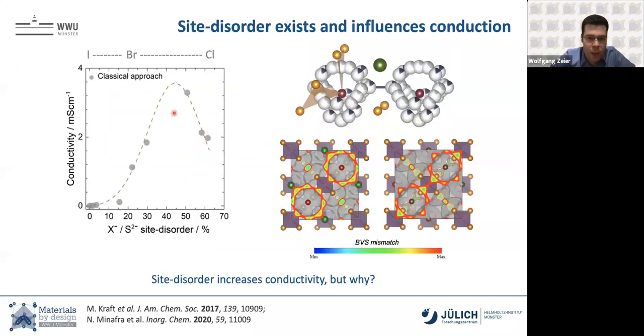Well, why certain compositions? There's something that we call site disorder in these materials. What is actually found is that depending on the halide that you use, some of the halide could be sitting on the sulfur site. This is very prominent in the chlorides. The chloride anion has the same ionic radius as the sulfur 2- anion, so in the synthesis, they can just easily exchange. So some chloride anion will be sitting here, some sulfur will be sitting here. And in the chloride case, this is roughly 50 to 60%, so really statistically entirely disordered.